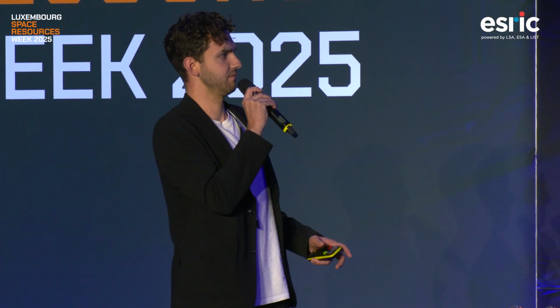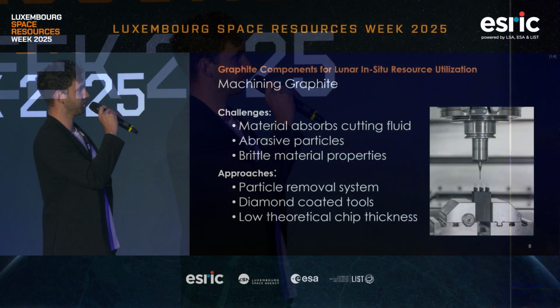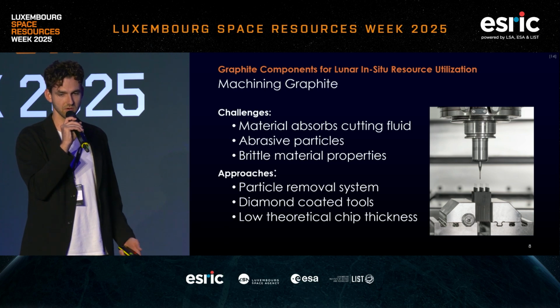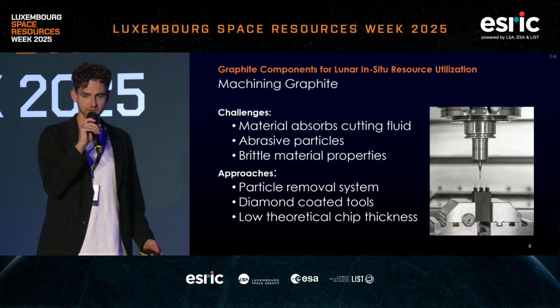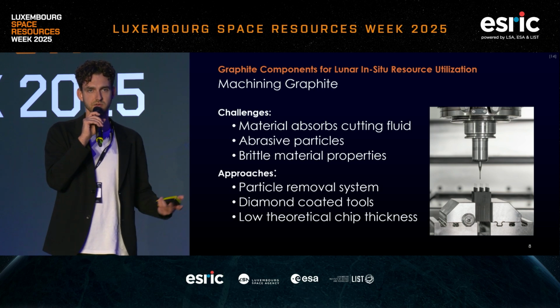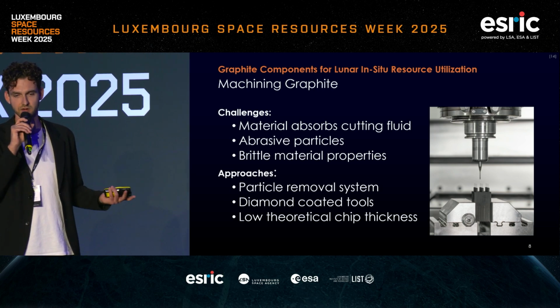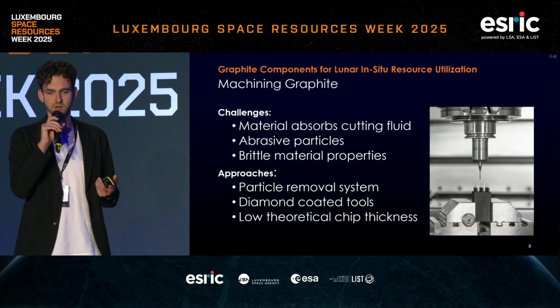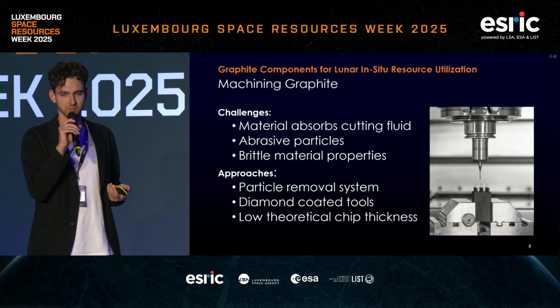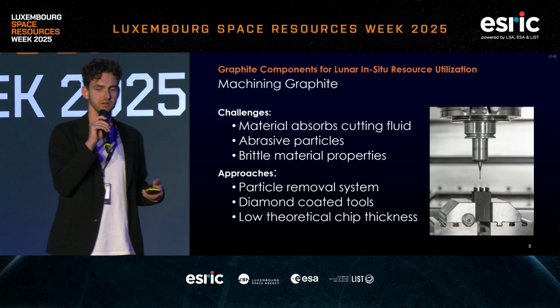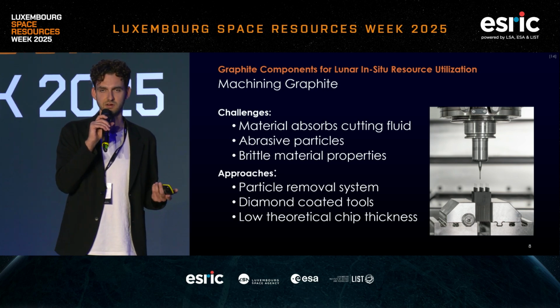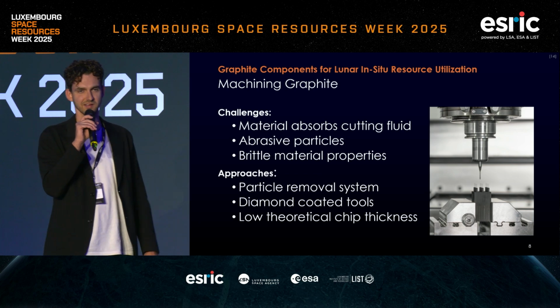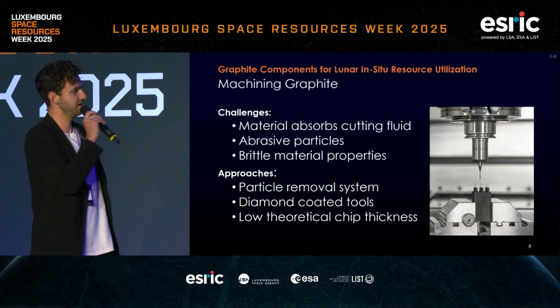destroy your tools and your machine. So yeah, you can't use cutting fluid, and you have to avoid some cutting properties because of the brittle material properties. So what are the approaches that we've utilized to overcome these challenges? First of all, we have a particle removal system that, with vacuum basically, gets rid of all the dust or the particles that are being created during the machining process. This is good for keeping the machine clean, but also for our health, because you don't want to breathe these carbon particles.